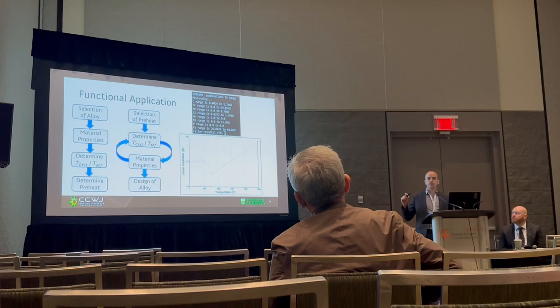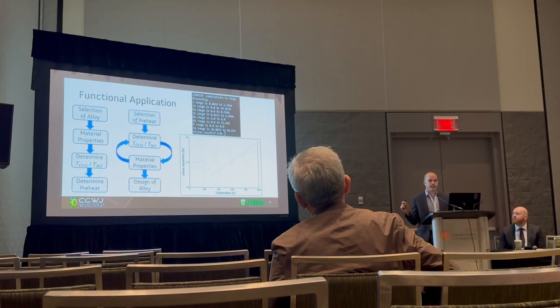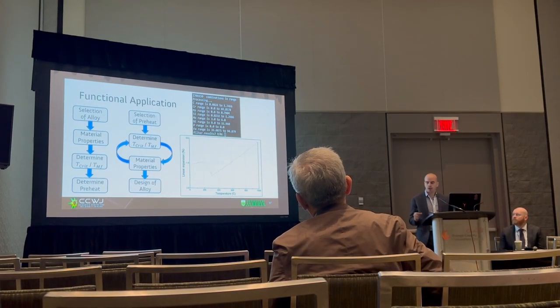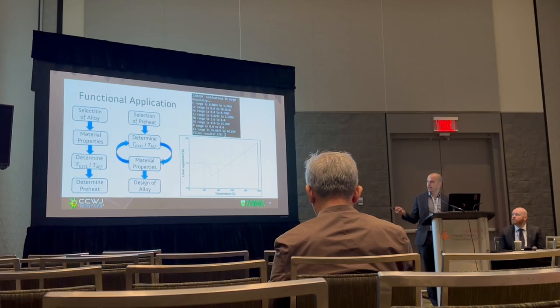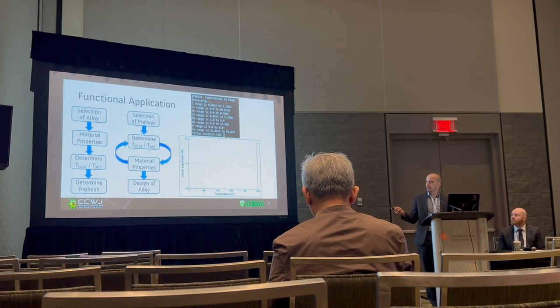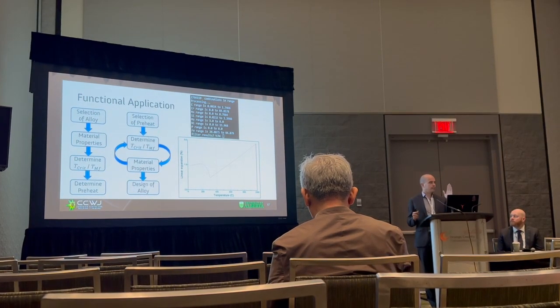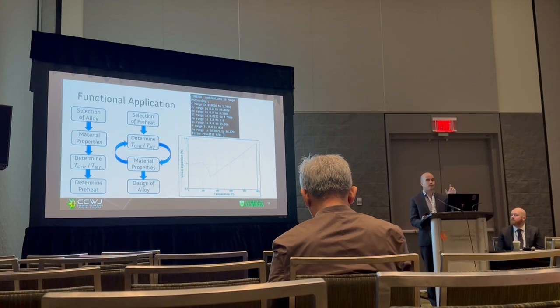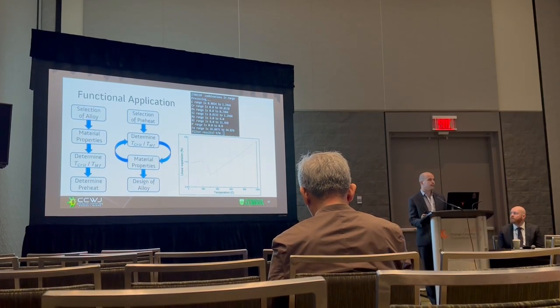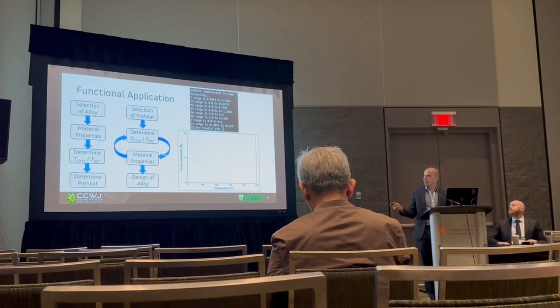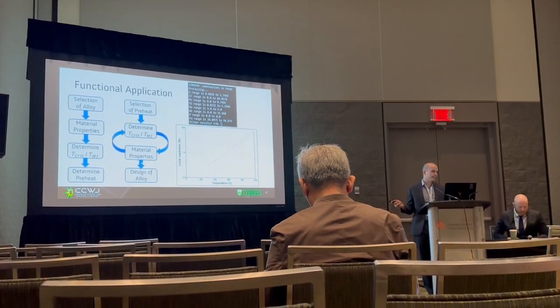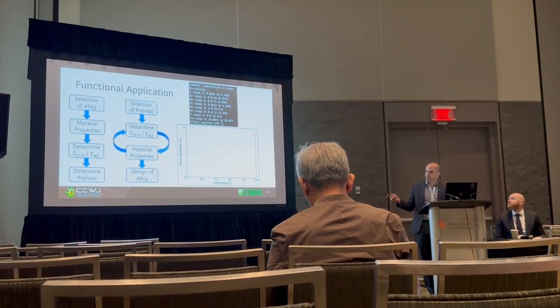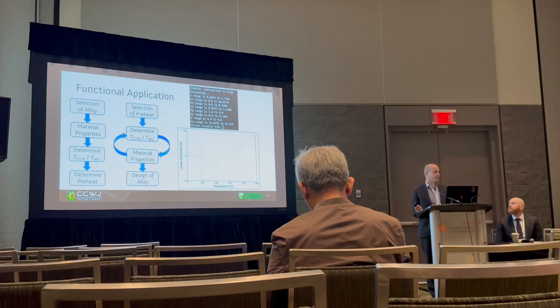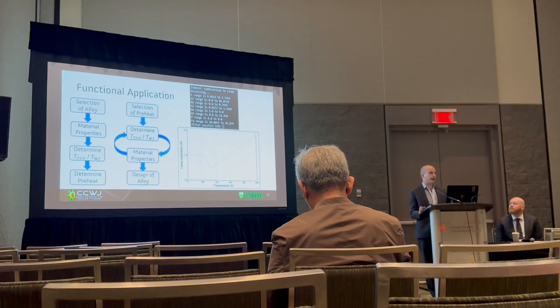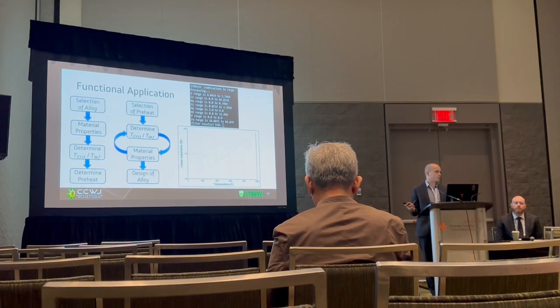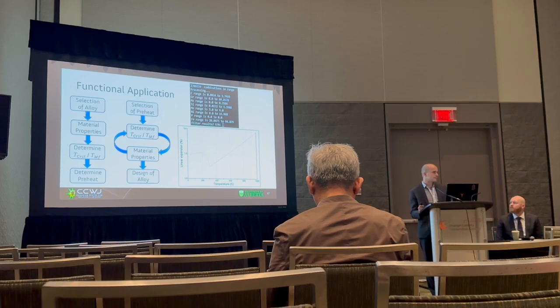Whatever material I choose has to retain some of that compressive residual stress when I bring it to room temperature. So I know that. That determines that T martensite finish and that delta T crit. So I know the temperature at which martensite completes and the range of temperatures I can work within to get that benefit. And then from there I know the material properties I need in my alloy. Then I did a bunch of simulation and I wrote some codes that allow me to pump simulation back and forth with alloy design, and I can design an actual alloy, and that's what's going into these train wheels.